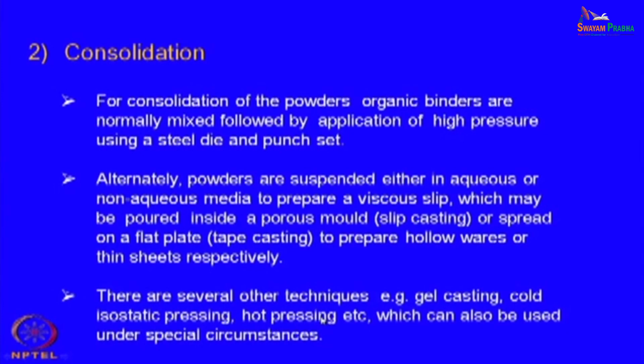You use an oil, and inside that you put the material, the powder, in the form of a flexible bag. You put it there and then pressurize the liquid, so that a uniform pressure is applied from all sides. That has its own advantage, because if the pressure distribution is not uniform and you have an inhomogeneous pore size to start with, at the sintering stage or the firing stage, there will be non-uniform porosity, and that will be a source of weakness so far as the strength is concerned. Okay. So, that is the reason one uses isostatic pressing.